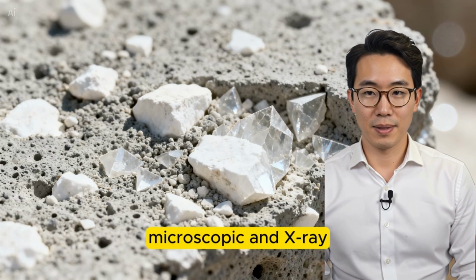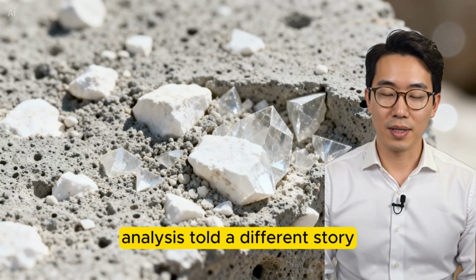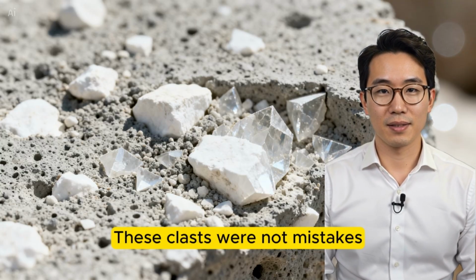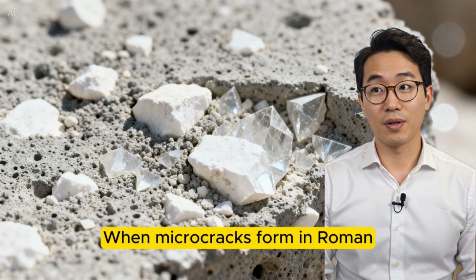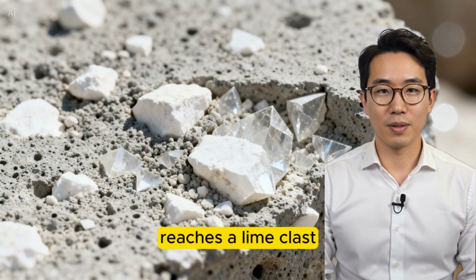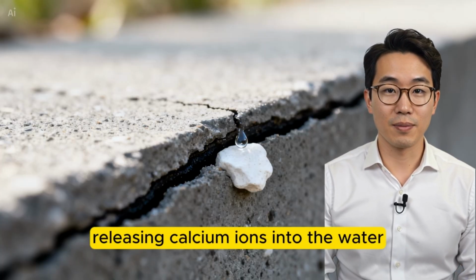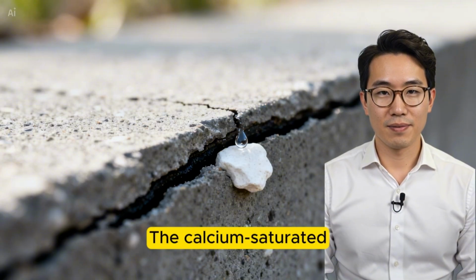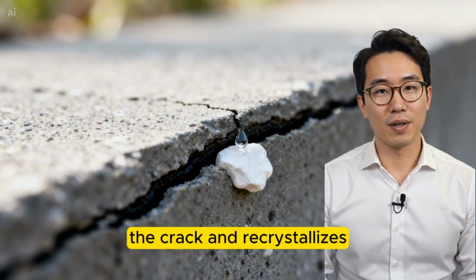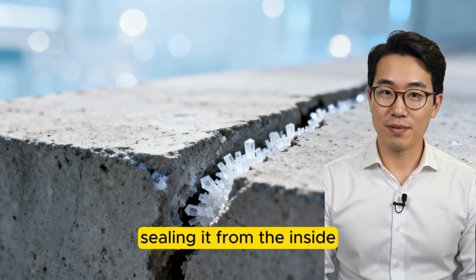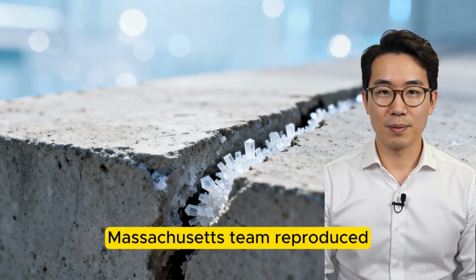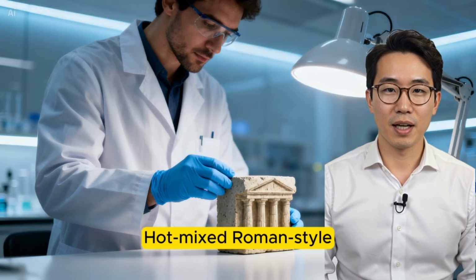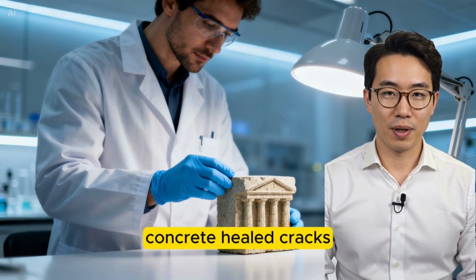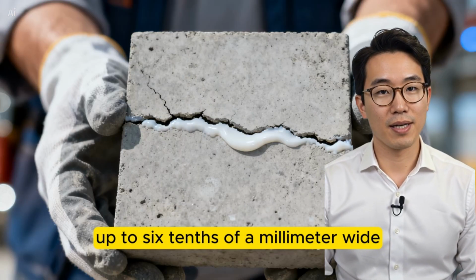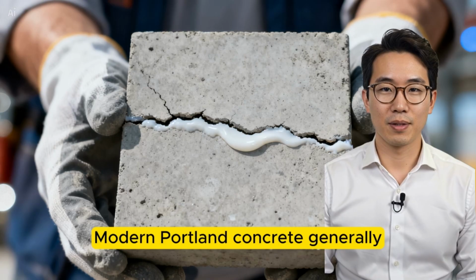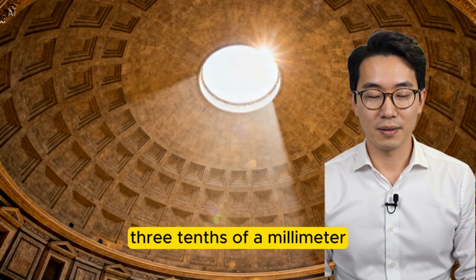The team's microscopic and X-ray analysis told a different story. These clasts were not mistakes, they were reactive reserves. When microcracks form in Roman concrete and water reaches a lime clast, the lime dissolves, releasing calcium ions into the water. The calcium-saturated solution flows back into the crack and recrystallizes, sealing it from the inside. MIT's team reproduced this effect in the laboratory. Hot-mixed Roman-style concrete healed cracks up to 0.6 of a millimeter wide. Modern Portland concrete generally cannot heal cracks beyond 0.3 of a millimeter.